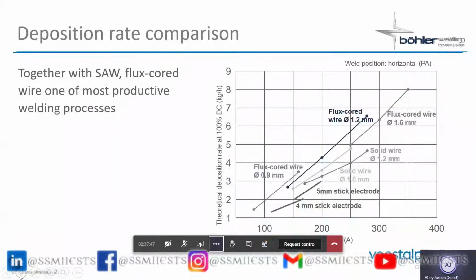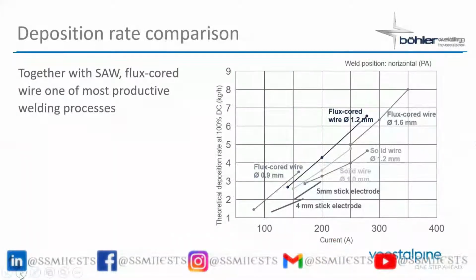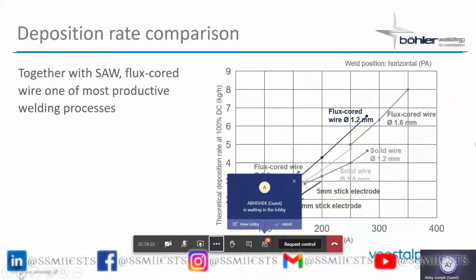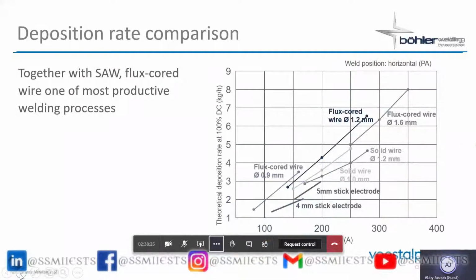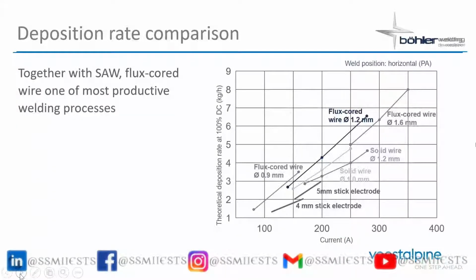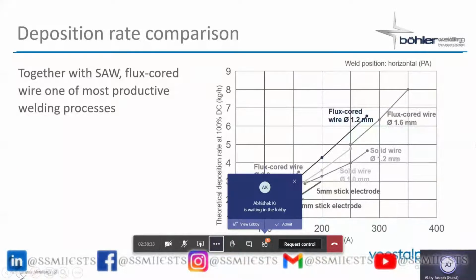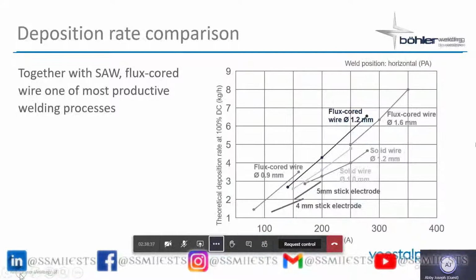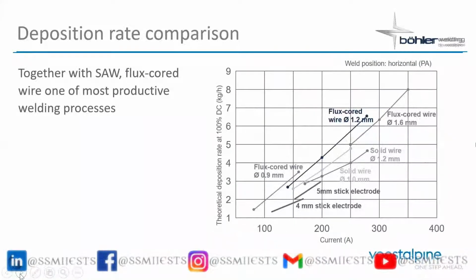Flux cored wire is also a very productive welding process. So you see here the productivity versus stick electrodes. If you see the flux cored wire of 1.2 millimeter, it can give you a deposition rate all the way up to about 6 to 7 kilograms per arc hour, compared to a 4 millimeter stick electrode, which can give at the most 2 kilograms per arc hour. So you have almost 3 times the deposition rate in flux cored wires compared to stick electrodes, and this is the reason flux cored wires are picking up more and more in India versus stick electrodes.